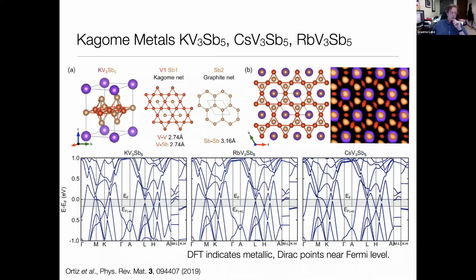And so what's interesting about this material is that the vanadium has a Kagome lattice, which you can see here in red, whereas the antimony forms this graphite-like layer, which I showed you a picture of earlier in that moire pattern. This graphite structure is also sort of the building block, if you like, of that Kitaev lattice. So it has a lot of interesting building blocks, and they're stacked up along the c-axis like so, with the potassium reasonably separate from the Kagome planes.